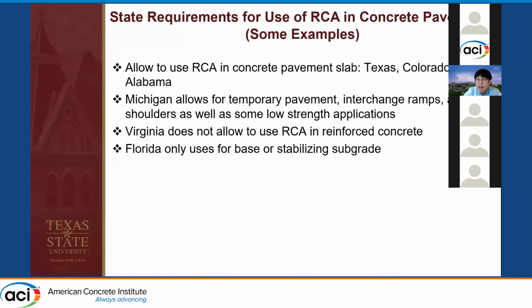However, the use of recycled concrete aggregate in pavement applications has not been widely accepted by a lot of states. Based on a recent survey, we're just showing some examples here. Texas, Colorado, and Alabama allow the use of RCA in concrete pavement slabs. Michigan allows it for temporary pavements and also some low strength applications. Virginia does not allow the use of RCA in reinforced concrete because they were worried about the chloride content in RCA. And Florida only uses RCA for base or to stabilize the subgrade. Again, these are some samples. There are many other examples we probably haven't learned about yet.